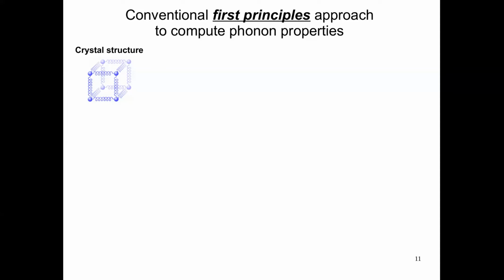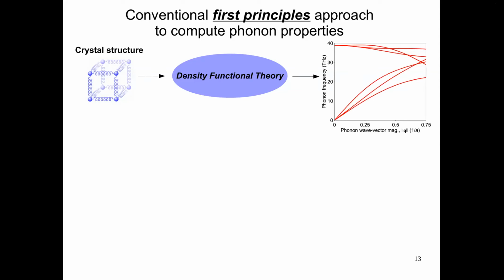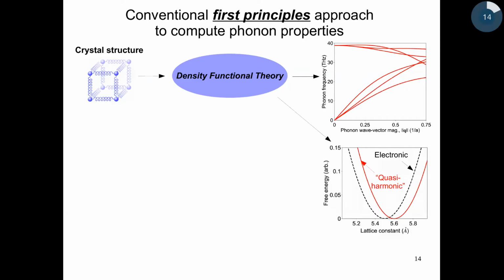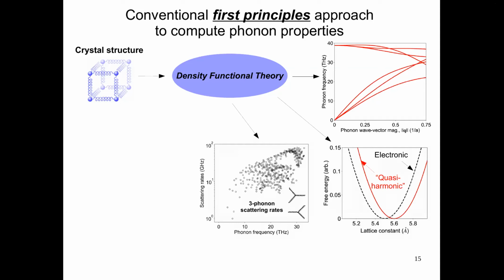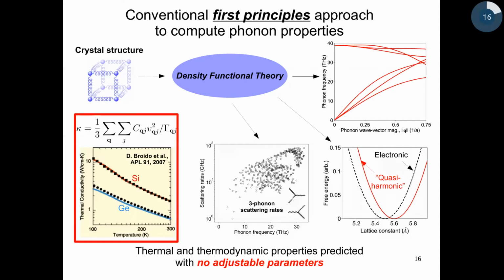That's it. With just this information, we can crank it through the density functional theory machinery and calculate properties such as phonon frequencies, dispersion, the free energy, including the vibrational component, phonon scattering rates, and putting these all together, we can also calculate the total thermal conductivity of any material without any adjustable parameters. In the red box on your left is one of the first examples of the work from my postdoctoral advisor's group, where they used this density functional theory machinery to accurately predict the thermal conductivity of silicon and germanium over a broad temperature range without any adjustable parameters.